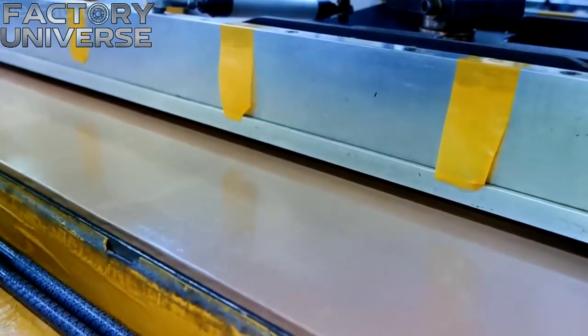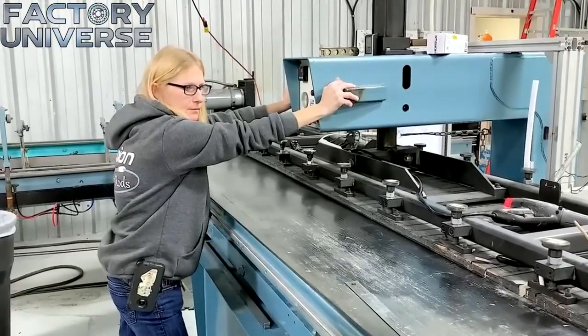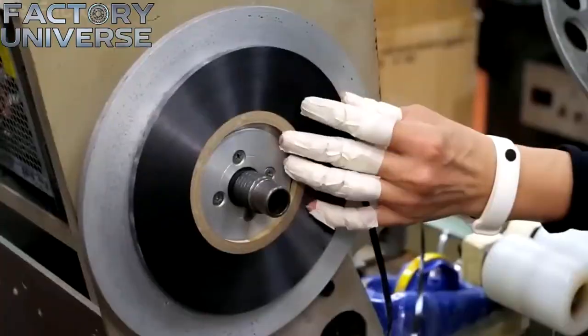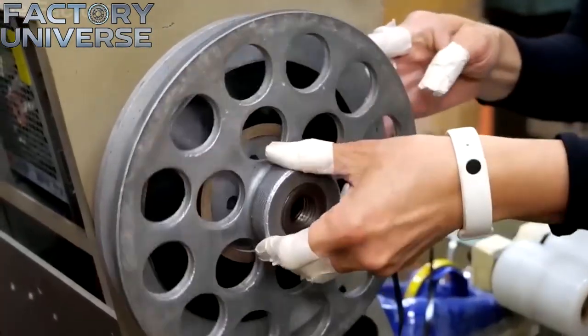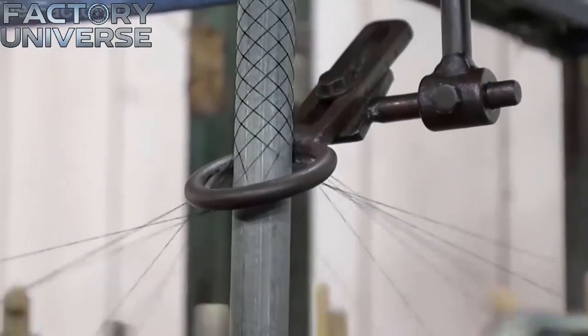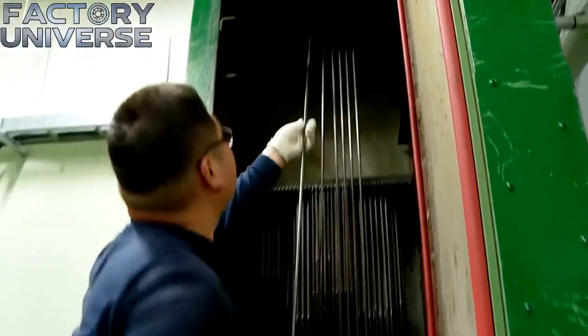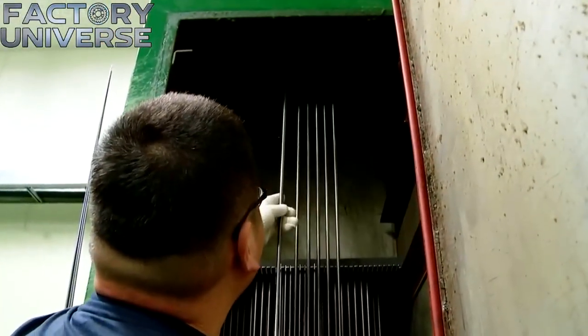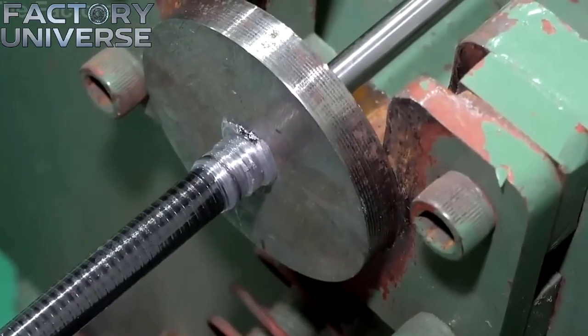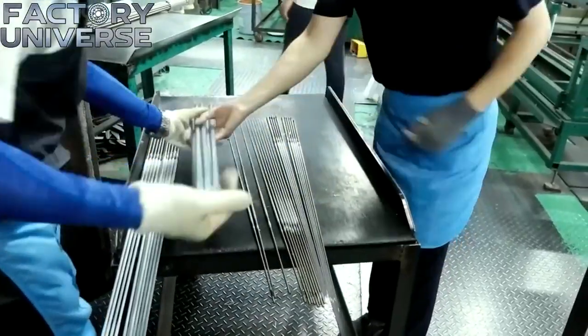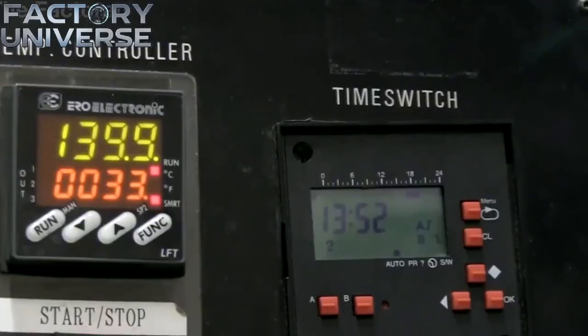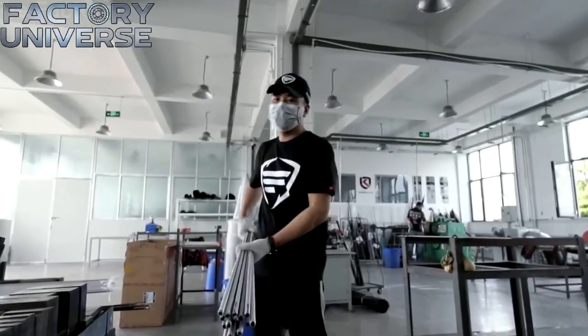The rod blank sits ready for the oven, held in a state of high mechanical tension. This concludes the primary shaping stage, opening the road to the final chemical transformation. 140 degrees Celsius is the typical temperature set within the curing ovens for the rod blanks. Once the mandrels carrying the carbon fiber components are secured with heat-resistant tape, they are hung onto specialized racks and moved into the thermal chamber.